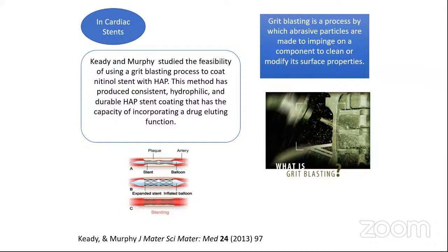Keady and Murphy studied the feasibility of using a grit blasting process to coat a nitinol stent with hydroxyapatite. Nitinol is a shape memory alloy. It is a nickel titanium alloy, and it has a shape memory. And this method has produced a consistent, hydrophilic and durable hydroxyapatite stent coating that has the capacity of incorporating a drug-eluting function.